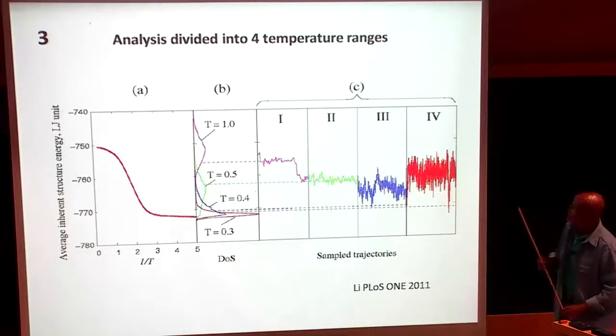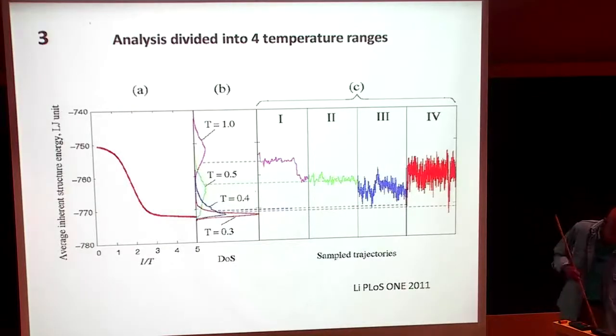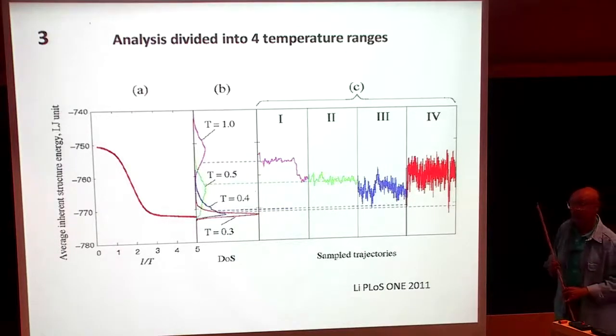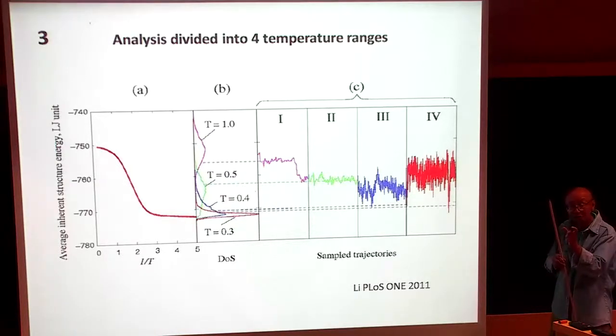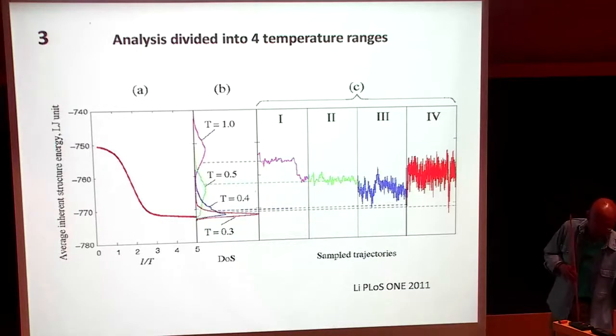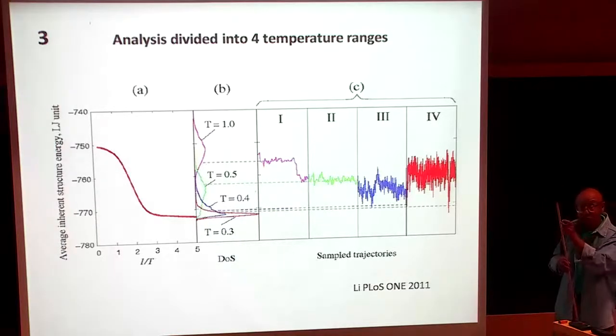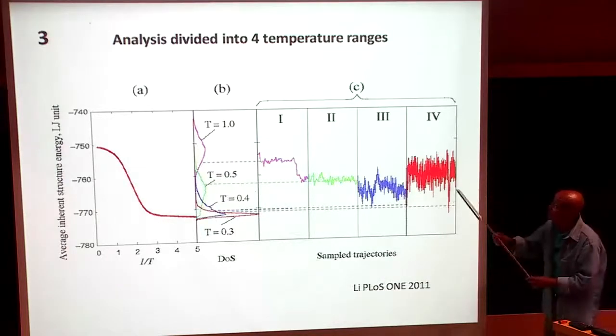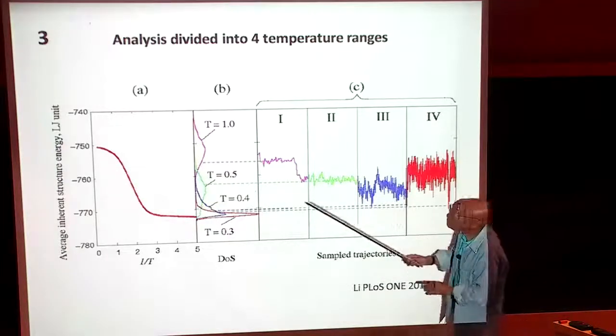It turns out that we realize that we don't want to calculate the viscosity at any arbitrary temperature, even though we want to cover the viscosity over a certain range of temperature. So we took that range and broke it into 4 separate regions. You remember now, this is the inherent structure.